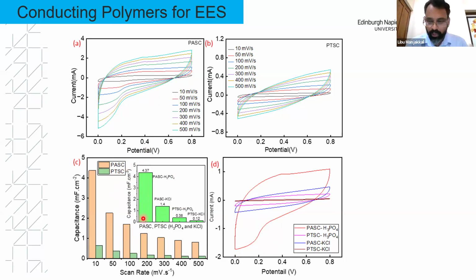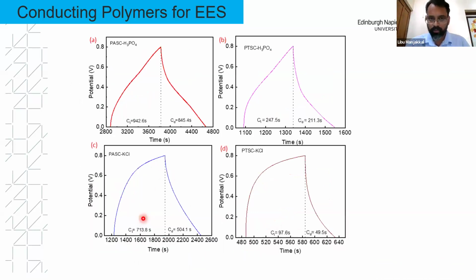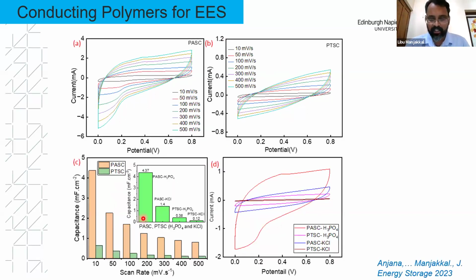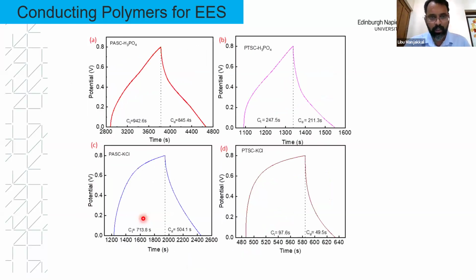Now what we are going to do is make composite structures of the conductive polymer with a metal oxide, because in one of the recent works we found that metal oxide alone offers less performance for energy storage device fabrication. But when you make the conductive polymer composite for printing technology, you can easily make a flexible substrate for energy storage. Here you can see the charging discharging cycle for the different conductive polymers, and you can see almost 90% efficiency for a polymer based device.